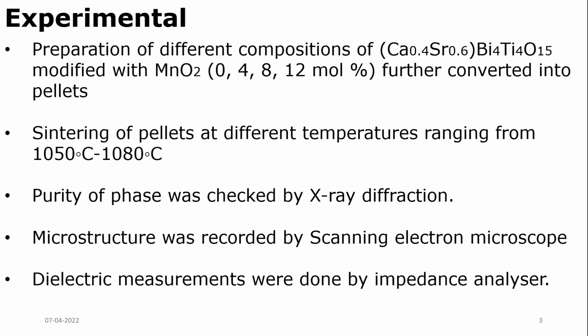We have prepared different compositions of CSBT with different concentrations of MnO2 by the simple conventional solid state reaction, which have been further converted to pellets. The sintering of pellets has been done at different temperatures ranging from 1050 to 1080 degrees Celsius. We have used XRD to check the purity of the phases. SEM and EDS have been done for microstructural and elemental analysis, and further electrical properties have been analyzed by an impedance analyzer.